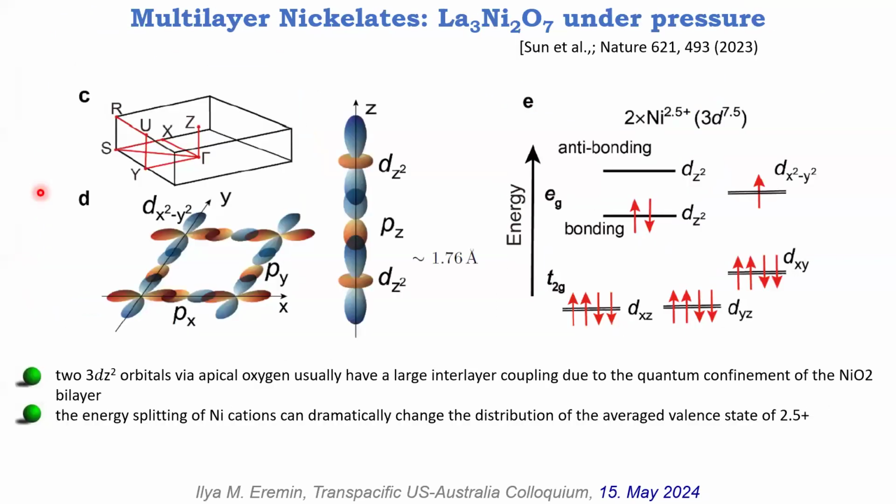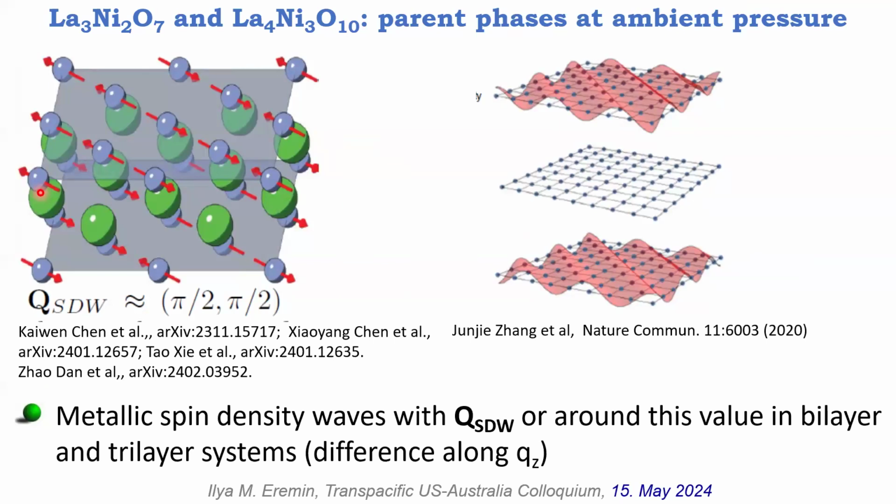Yeah, so that's maybe what I should also mention for the infinite layer nickelates. People have done the measurements also on the infinite layer, and fitting this with a Heisenberg type of model, you also get of the order of 60, 70 meV. So it's twice smaller than cuprates, and the critical temperature is also twice smaller. Kind of, yeah. Again, there is still material dependence. I would say for the bilayer nickelates, it is of the order of bilayer cuprates, so of the order of 80 Kelvin, but you're right, one could connect it to this.